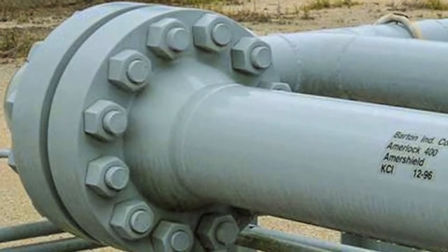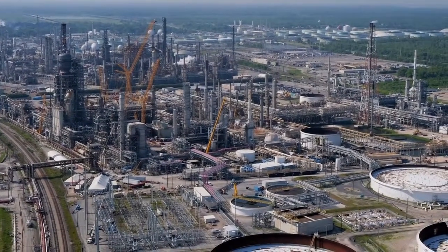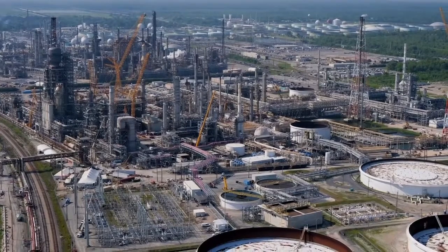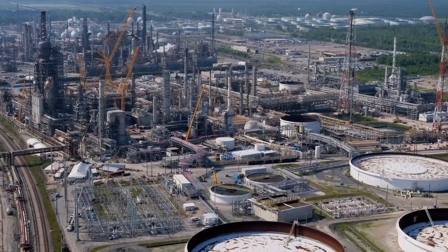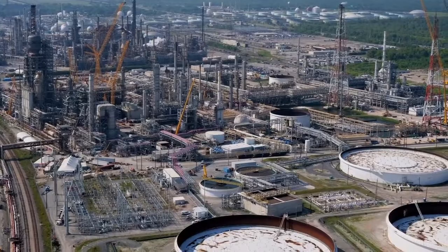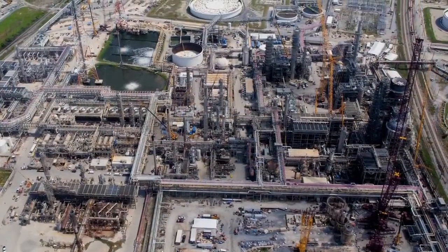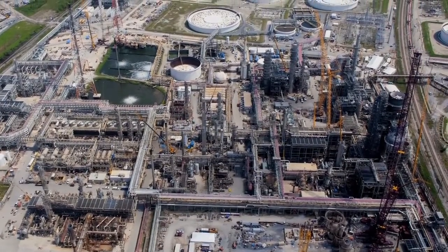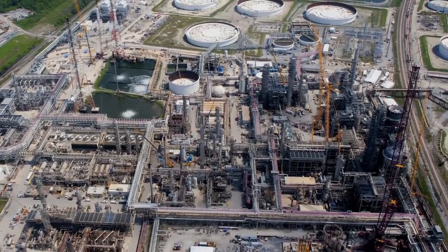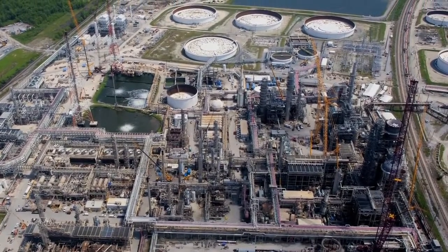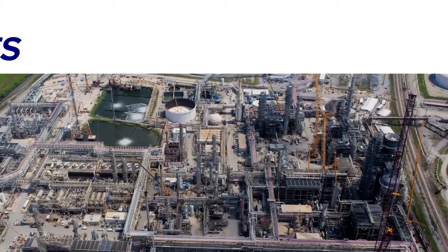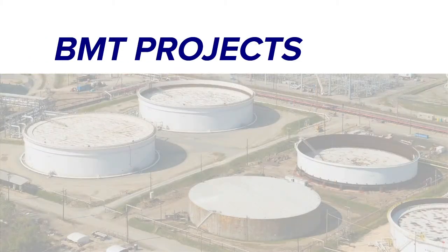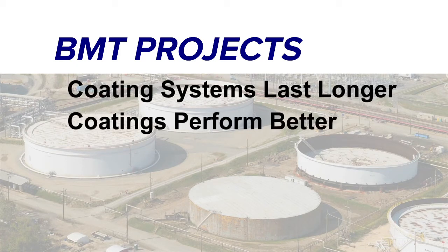One major client refinery on the Gulf Coast uses BMT to remove contaminants from the steel floors of above-ground storage tanks. Prior to using BMT, a combination of multiple abrasive blasts and competitive methods could not completely remove the floor contaminants. Using BMT to decontaminate metal tank floors has become a standard practice in this facility. By eliminating contaminants, BMT assures coating systems have a longer service life and perform exponentially better. It also makes an immediate difference at the project level by eliminating variables that accelerate costs and asset downtime.